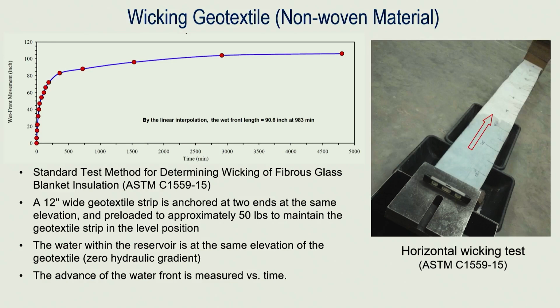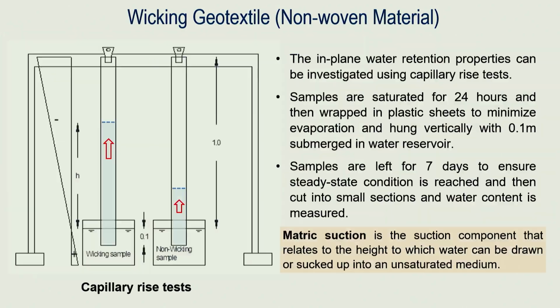One of them is the capillarity test. This is a standard test used in research. And the idea is you basically lower one of those strips into a container and allow the water to be sucked up towards the top of the strip and measure, in this case, what we call matric suction. In this context, it's the suction component that relates to the height to which water can be drawn or sucked up into the unsaturated medium.